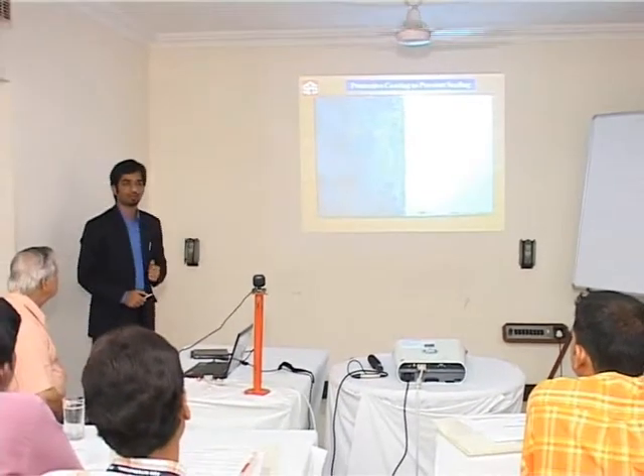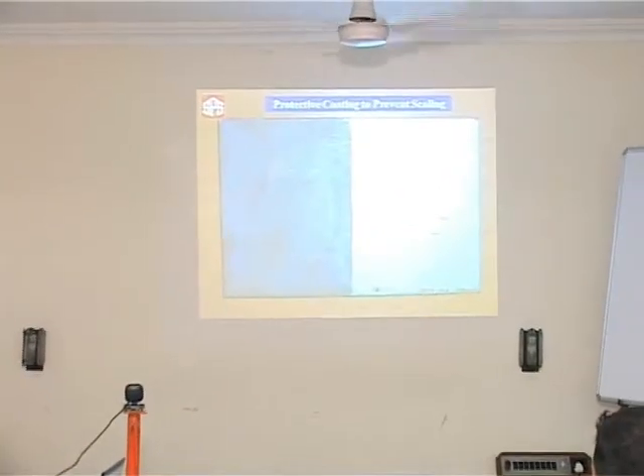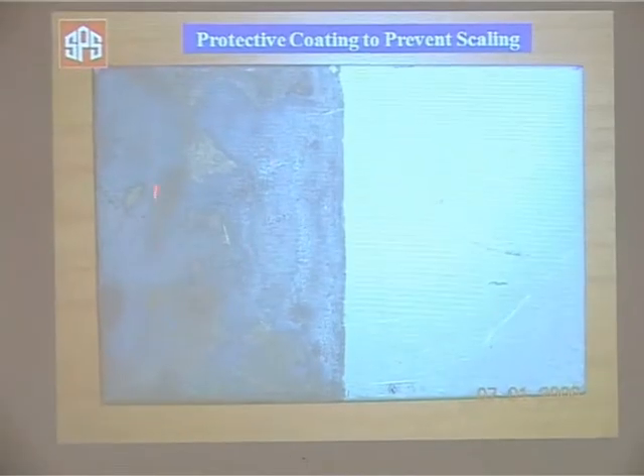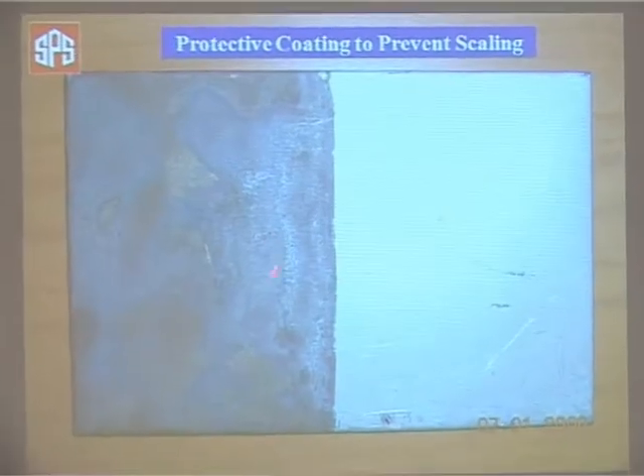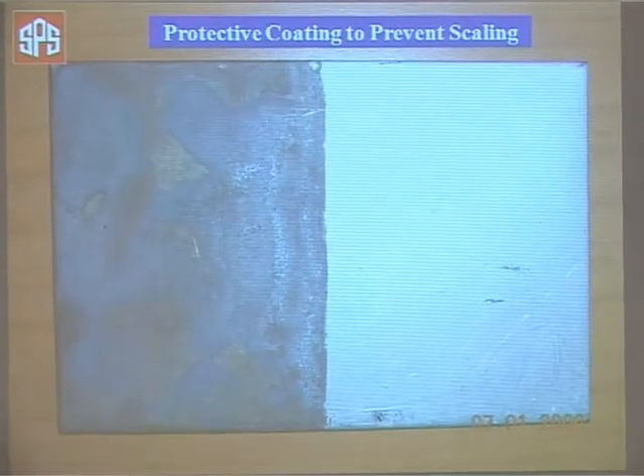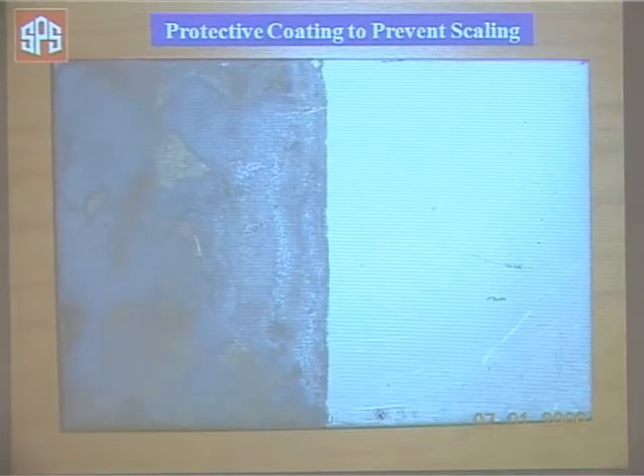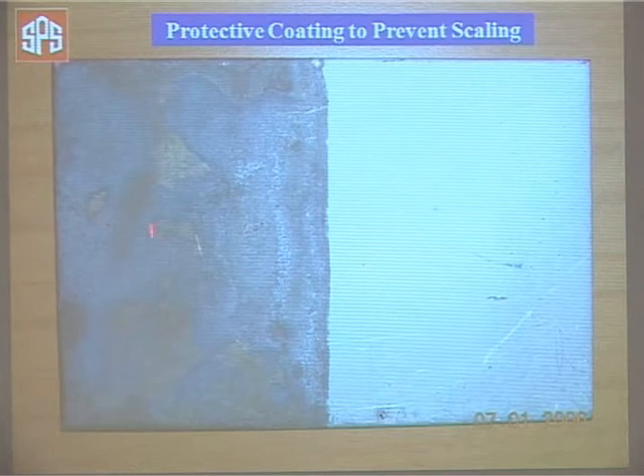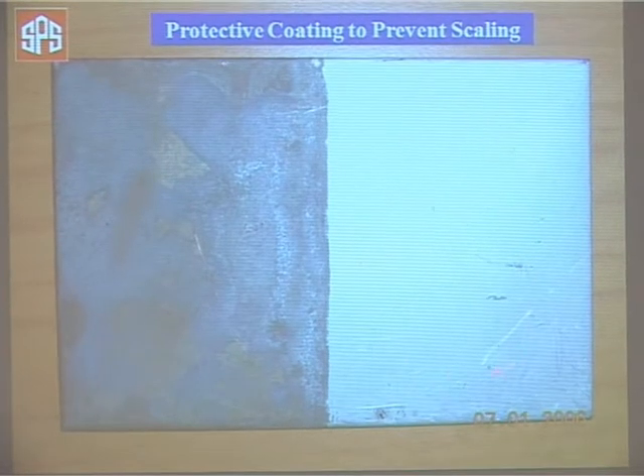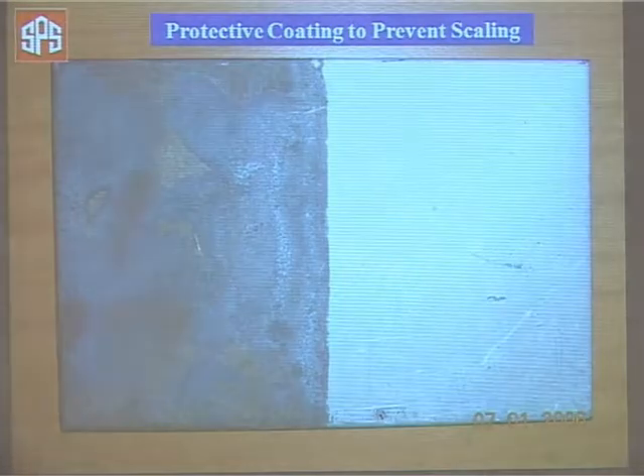This is a stainless steel sheet. As you can see, this half of the sheet was coated with an anti-scale compound, and after heat treatment, after solution annealing, and a little bit of buffing, you can see the remarkable difference between the not coated area, which is over here, where scaling has developed, and the aesthetic appeal of the sheet is spoiled, and you can see some pit marks over here, whereas over here you can see a fairly good finish.